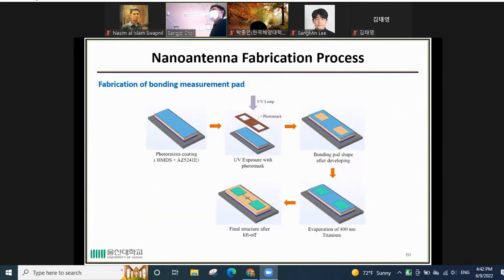And also for measurement, we also fabricate the bonding pad. Also, we start from the photoresist coating, and we develop the shape of the bonding pad with a photomask using UV lithography. So after UV exposure, we have the bonding pad shape after developing, and then this is the evaporation of 400 nanometer thickness for the bonding pad, and this is the final structure after the lift off process. So we have nano antenna, nano thermocouple, and bonding pads for measurement.